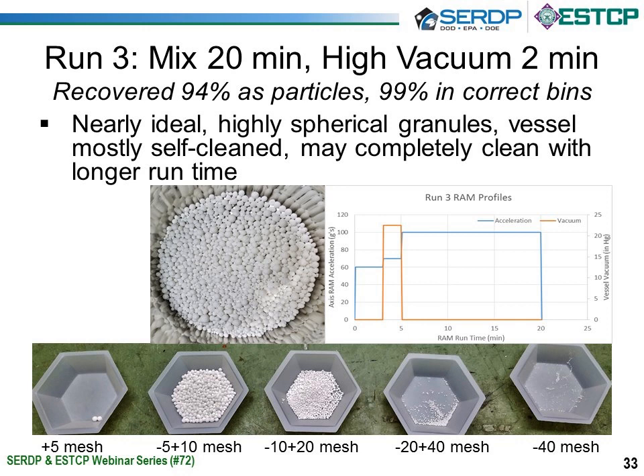You can see that the majority of the material is in the minus 5 to plus 10 mesh and the minus 10 to plus 20 mesh. We had two small granules in that plus 5 mesh, and we had very minimal material of the very small granule sizes in those far right-hand mesh bins. So here we settled on what we determined to be the optimal mixing and generation of that material. Again, we were able to recover 94% as particles and 99% in the correct bins. We believe that we could completely clean with slightly longer runtime and actually increase that 94% closer to 99%. Slide 34, please.